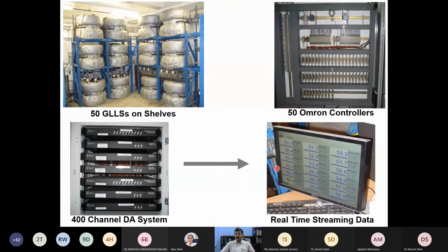And these are the temperatures at which I'm conducting the tests. One is 85 degrees. I'm supposed to maintain it at 85, but it may go up to 85.4 or down to 82.6, something like that. And we have tested a wide range of configurations and a wide range of temperature conditions and leachate recirculation states and a wide range of applied pressures.